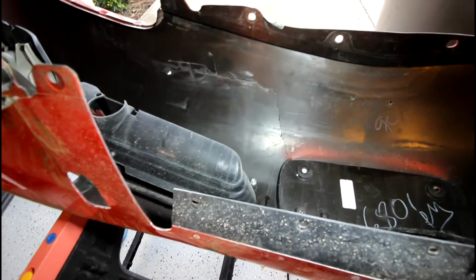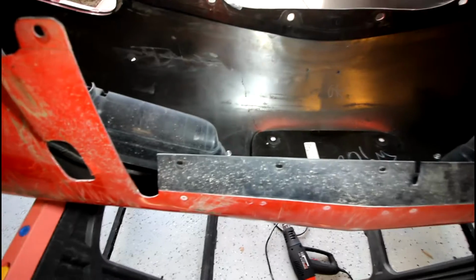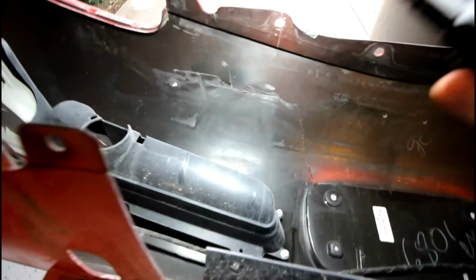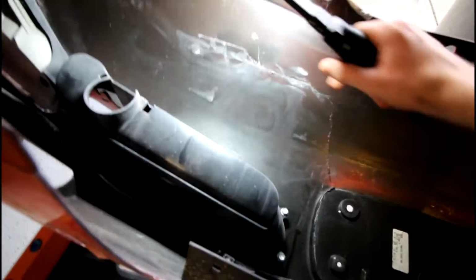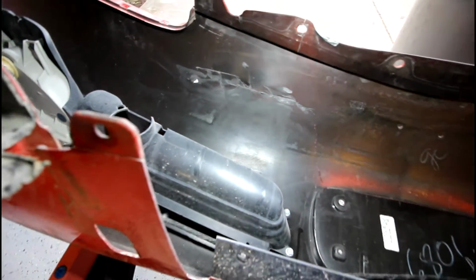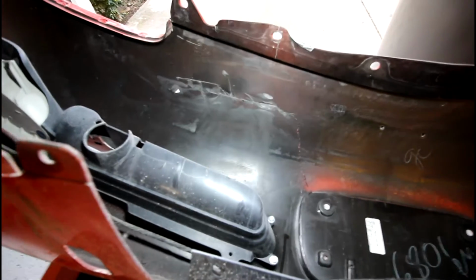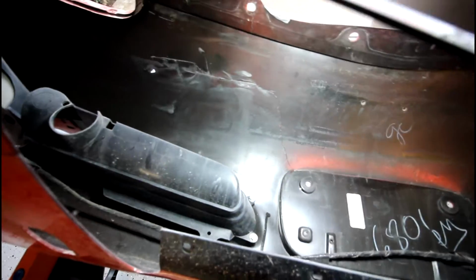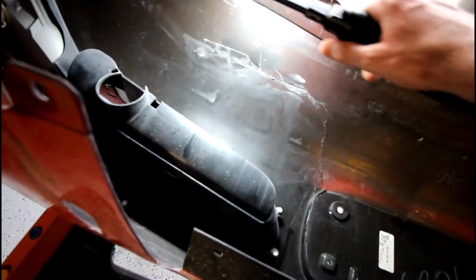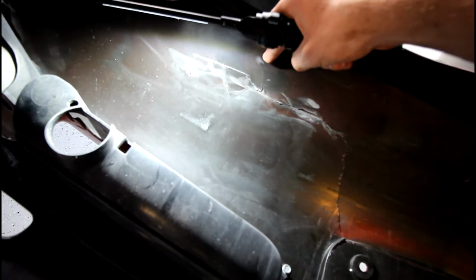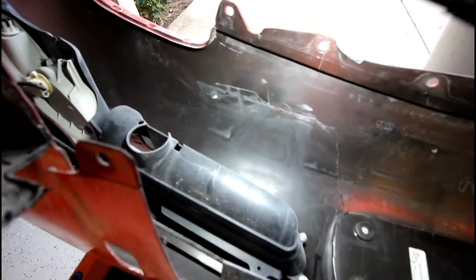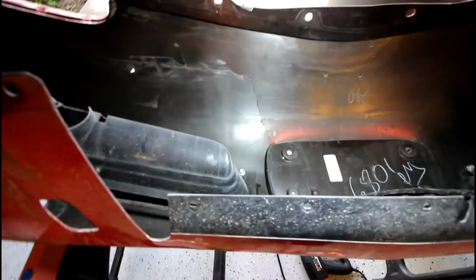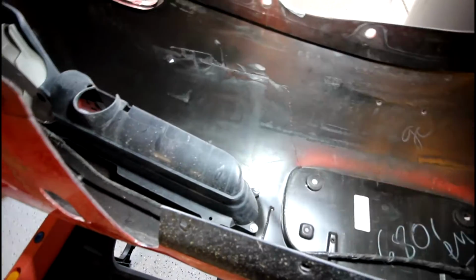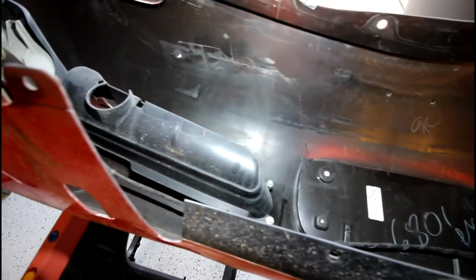And another thing that you can do at the beginning here is take a small drill bit and find the point where the crack stops, and drill a small hole at the end of the crack. Because the ends of cracks are stress concentrations, when there's flexing in the bumper, there is a greater chance for the crack to propagate and grow if you don't drill out the end. So you do your best to find the ends of the crack. Like there's one here, one right about here, and just drill out a hole, because then it decreases that stress concentration and makes it less likely that the crack will grow even after the repair is finished.